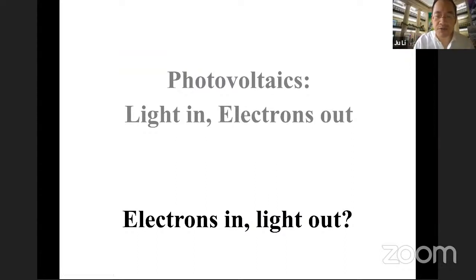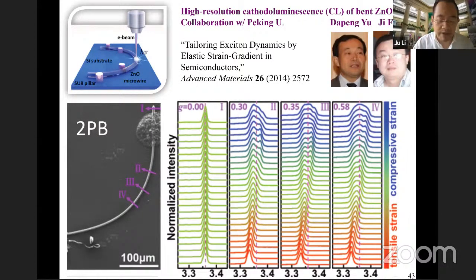So that was photon in, and you try to get electron carriers out. There is also an opposite demonstration, which is what if we send electrons in and collect the photons? So Ji was my postdoc. He went back to Peking University and collaborated with Professor Da-Peng Yu. So what they did was in the scanning electron microscope, they have a photon detector, and they just use the electron beam to scan here, here, here, here. And they move from the outside to the inside. And as they excite this zinc oxide microwire, the diameter is about 4 microns, the light detector just analyzed the color of the light.